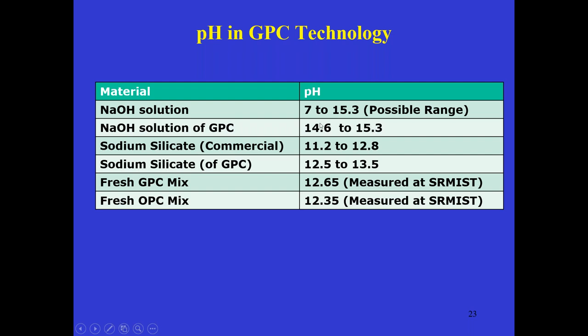In our geopolymer system, we never use less than 14. Okay, because 10 molar is the most commonly used, and more than that. You can see here sodium silicate solution in the market has a pH of only 11.2 to 12.8. When you mix these two, we get only 12.5 to 13.5. Whereas this, you can see pH is 14 and 15. It never comes into the sodium silicate solution.